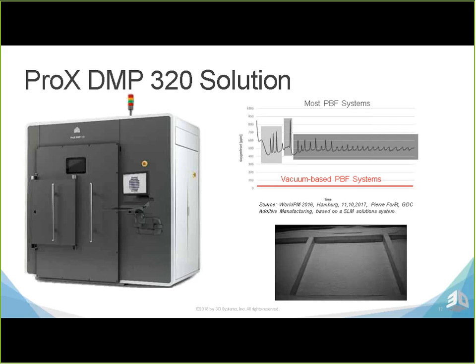or a nitrogen, and then every time material is deposited across the powder bed, what you'll see is a spike in oxygen content. So remember this, as fun as 3D printing is, it really is nothing more than a very advanced welder with a very fine powder. And so, a critical step in welding is how much oxygen is at the weld bed. So now, if you're operating with a system that is relying solely on purge, what you'll find is every single time you have a layer deposited of powder, you have a spike in oxygen content. So the majority of non-vacuum-based systems are going to operate between 500 and 1,000 parts per million. What this does is it really drives oxygen at the weld bed itself.